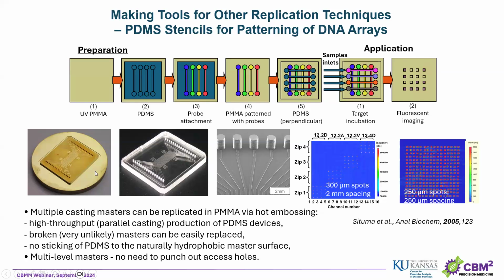And the way we've done it was that we first micromill the mold, out of which we replicated the PMMA casting tool, right? And you can see again, the same tool has both micro and macro structures, and we were able to cast PDMS out of this to pattern arrays. And I believe back then the best we could do was spots about 250 micrometers with 250 micrometer spacing.